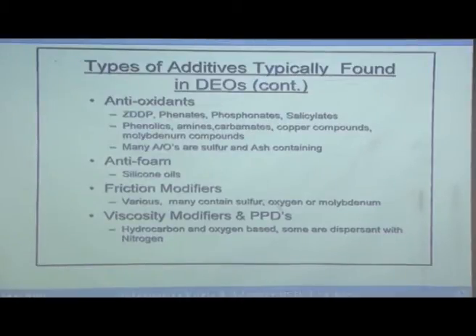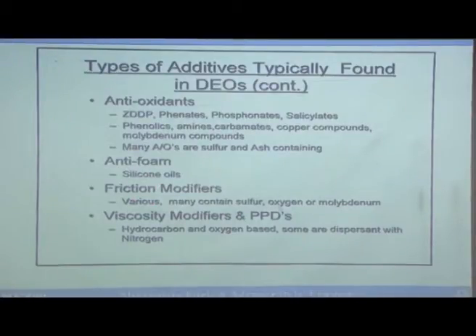The most important antiwear agent is ZDDP — zinc dialkyl dithiophosphate. ZDDP also acts as a corrosion and rust inhibitor. Other rust inhibitors include triazoles and thiodiazoles. For antioxidants, ZDDP is again one of the most important, along with phenates, phosphonates, and salicylates. Silicon oils are used as antifoam agents. Viscosity modifiers include hydrocarbon or oxygen-based compounds.